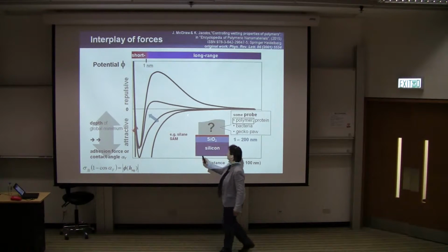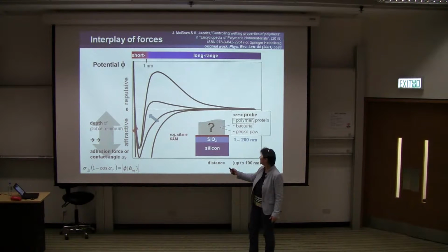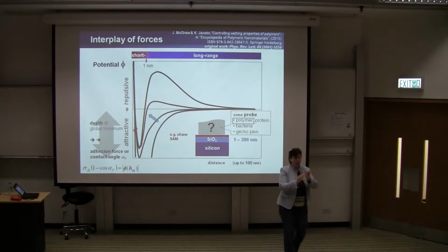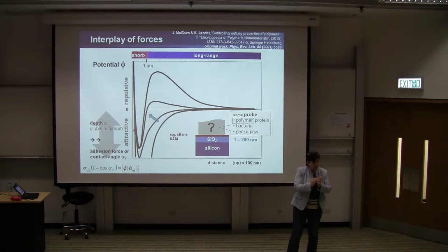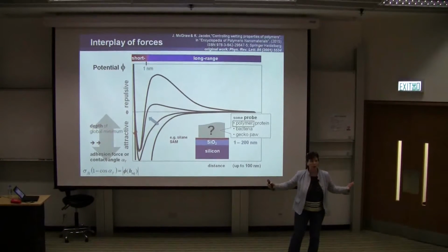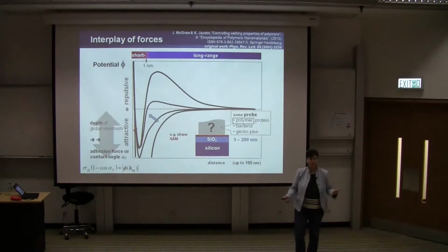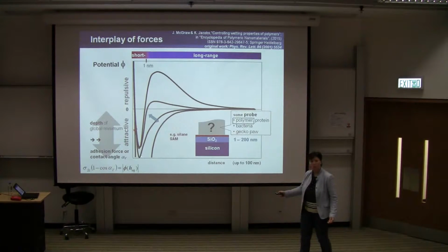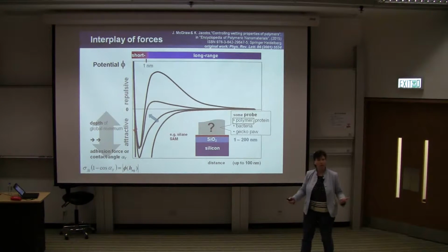So if we prepare the 10 nanometer photoresist in one of those two situations here, where we have a purely attractive force between the interface air-liquid and liquid-solid, if the force is attractive, this means the liquid photoresist is pushed out and it will de-wet. So this is the nightmare for Intel and all these companies. So this means that the system will slide into its equilibrium position and de-wet.